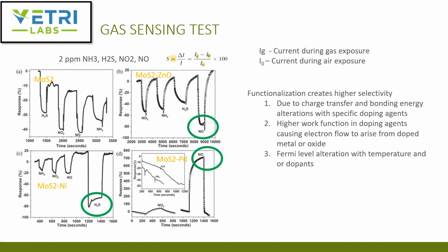And if you look at it, the same nitric oxide in the zinc oxide scenario shows a negative response. And the same nitric oxide with palladium, moly sulfide doped with palladium, shows a positive response. It's the same gas, but two different responses. And their theory is it is due to the chemical potential of nitric oxide with respect to the chemical potential of moly sulfide palladium or with respect to the zinc oxide. Obviously, the chemical potential gradient will drive electrons one way or the other.